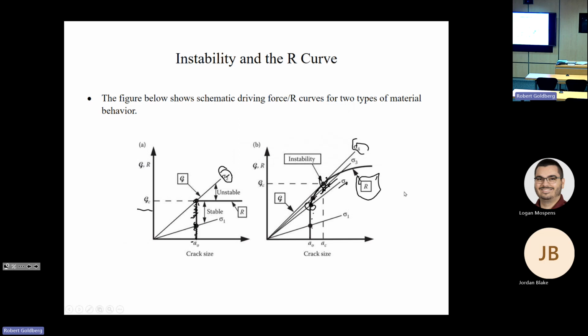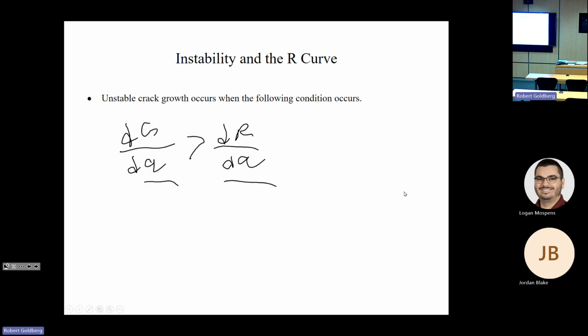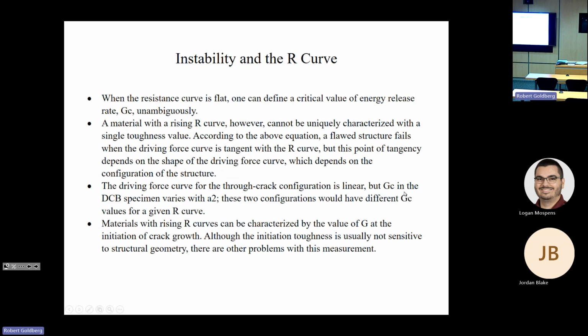So this curve here will look, for the case of a through crack, like nice linear curves. For a DCB specimen, they would be quadratic curves. So the resistance would still have the same shape, but the shape of this strain energy release rate versus crack size will be different. So the different configurations have different GC values for a given R curve. So materials with rising resistance curves can be characterized by the value of the strain energy release rate at the initiation of crack growth.